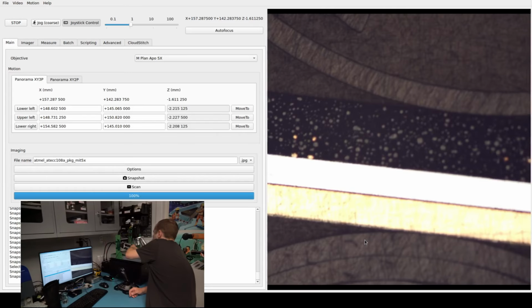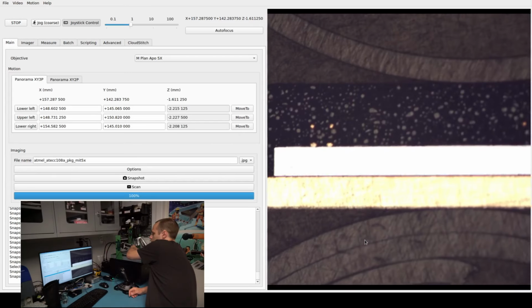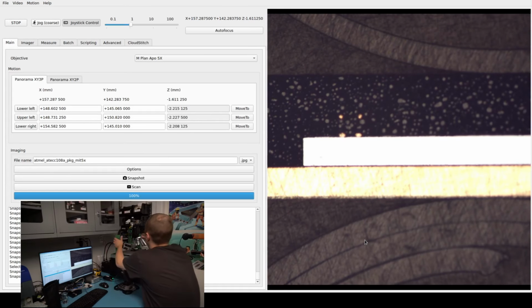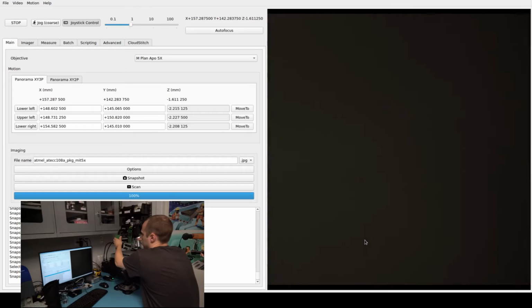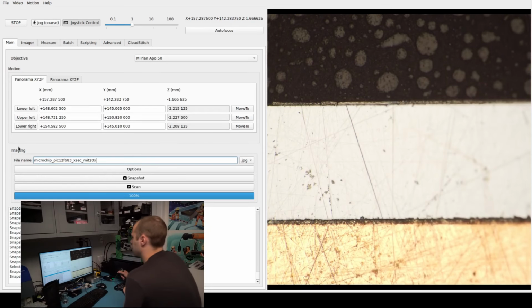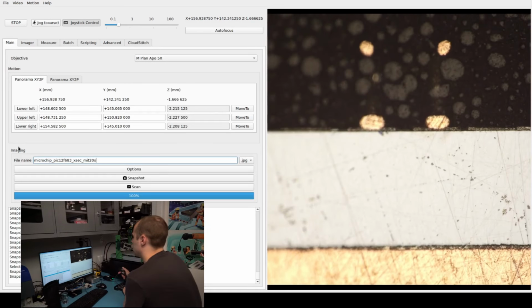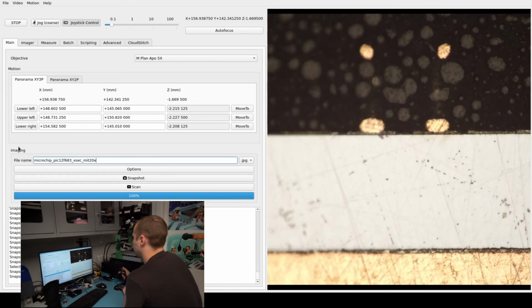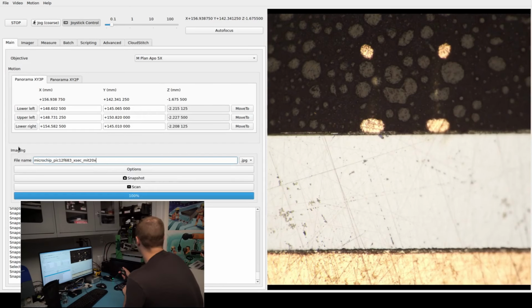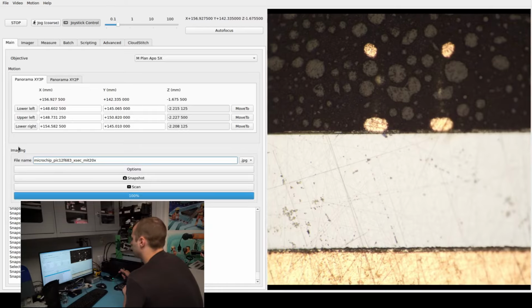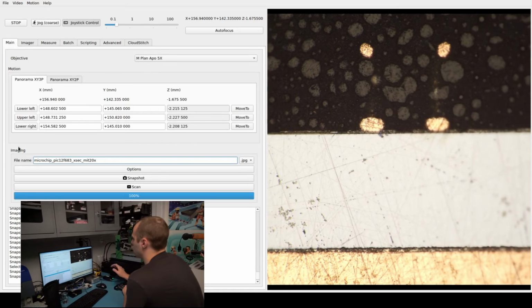We're going to get the sample roughly positioned on the stage and get a bit more 20x objective, and then get at least a rough idea of where. So we can see the sample is a little off level. I didn't bother to get it precisely positioned since we're just doing a quick in-process view to see how things are going with the polish. There's still a bunch of scratches. That's to be expected at this stage of the polish. We're not expecting to be at a perfect finish until we switch to some finer abrasives, but we're pretty close to where we want to be.